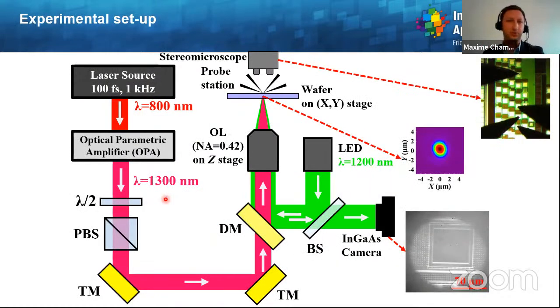To answer this, we have developed an experimental setup. I will not go too much into the details, but it relies on ultra-short laser pulses, so 100 femtoseconds at 1.3 micron wavelength. Then we control the energy by means of a half-wave plate and a polarizer, and focus the beam onto the microelectronic wafer. Besides, we have two diagnostics. First, a stereo microscope in order to make some 4-point probe measurements and eventually program and erase the device in situ. And also, represented in green, a microscope working in reflection for observing the microelectronic device and inducing the plasma near the flash memory.